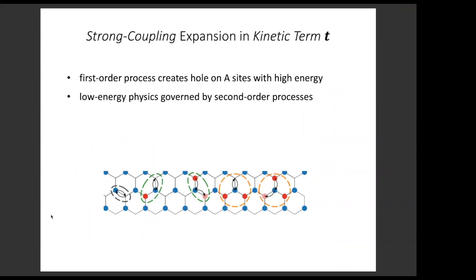Okay, so the method we're going to use is this strong coupling expansion in the kinetic term. In this model, we have only nearest neighbor hoppings. So if you want to describe to the first order in t, you always create holes on the A site, and this is a high energy excitation. Instead, in order to describe the low energy physics of doped electrons that live on the B sites, we have to start with the second order process. So we're going to now derive the second order effect.